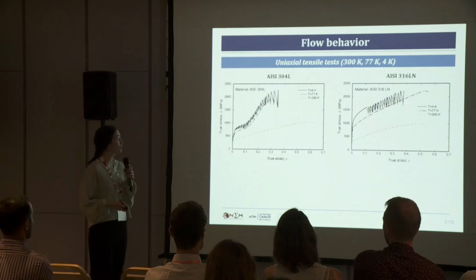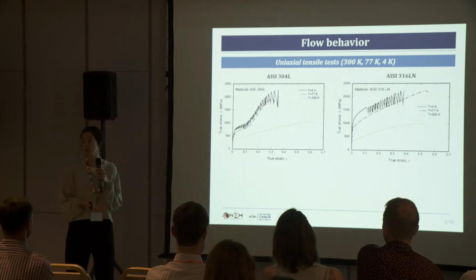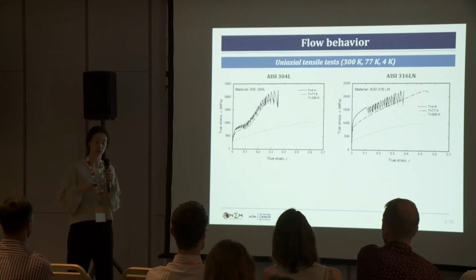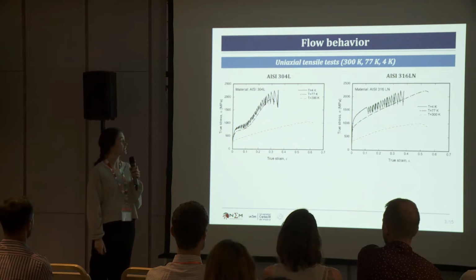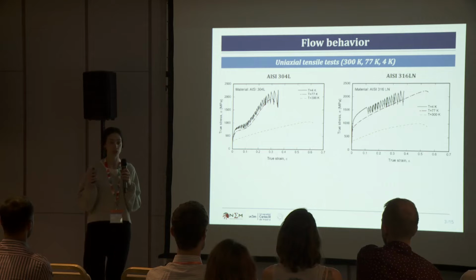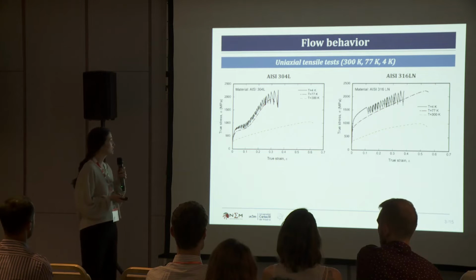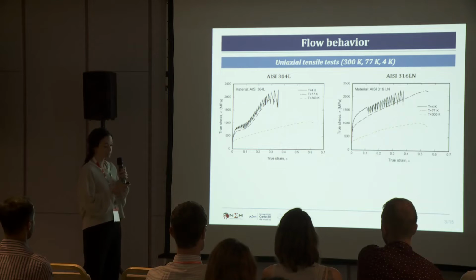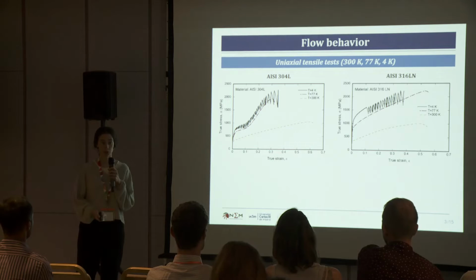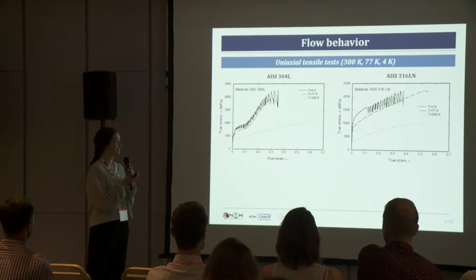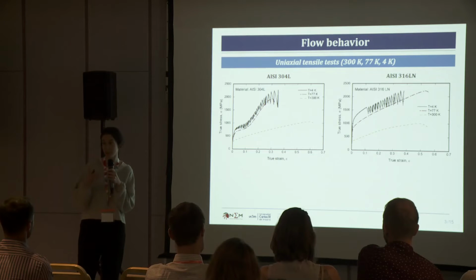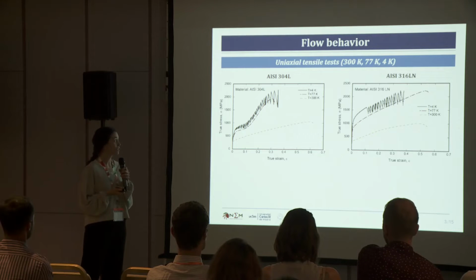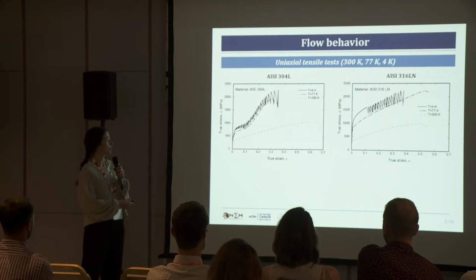So what we have done is to focus on two of the most dominant grades for this kind of application, that are the AISI 304L and the AISI 316LN. And the first thing that we have done is uniaxial tensile tests at 3 different temperatures: room temperature, liquid nitrogen temperature, and liquid helium temperature. And here you have the stress-strain curves. As you can see there, we have high ductility, strength, and toughness for the two grades at the 3 different temperatures. Indeed, in fact, this is one of the reasons why they are using this kind of grades for this application. You might be wondering now why we have these very interesting serrations for these two grades at 4 Kelvin.